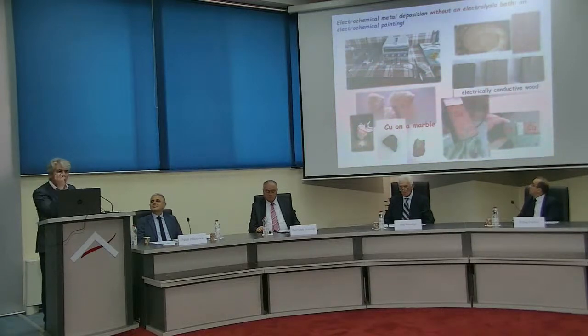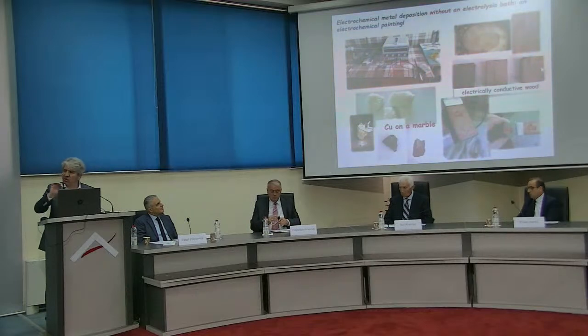And of course, that can be done with wood. That is very exciting, you know, to make a wood-metal composite, but a real composite, by electrochemical deposition. First, original wood, then covered with traces of electroless silver deposition. The wood becomes electrochemically, electrically conductive. Then I deposit copper on that, and I can further deposit silver. It is a sort of electrochemical painting, and I can explain it to my colleagues who are interested in that.